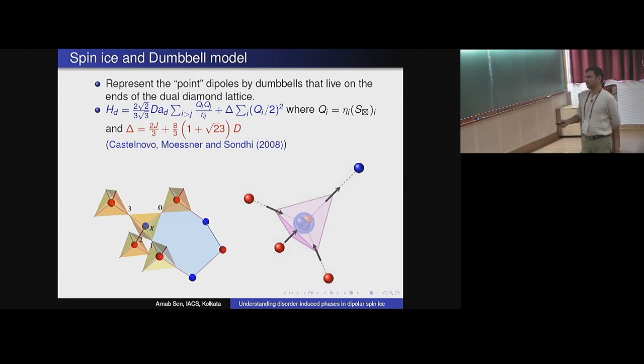So then this problem of spins gets converted into a problem of charges, and these charges are sitting at a finite temperature, if you wish, and then you can in fact use many intuitions from the Debye-Huckel theory of plasma as well. Okay? Good. So then for these dysprosium titanate and holmium titanates and these other compounds which show these spin ice behaviors, what happens is this delta is reasonably big compared to this other scale.